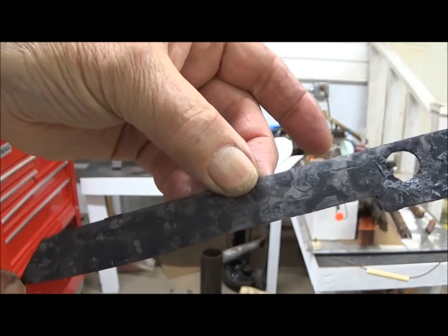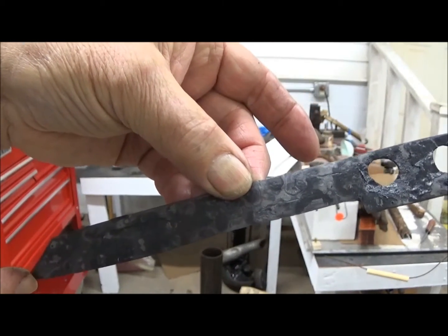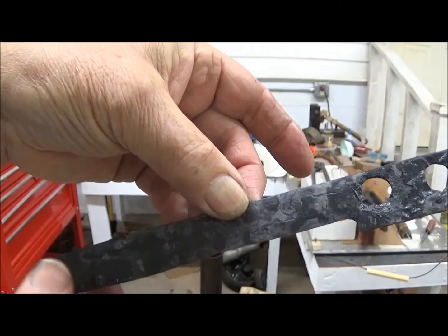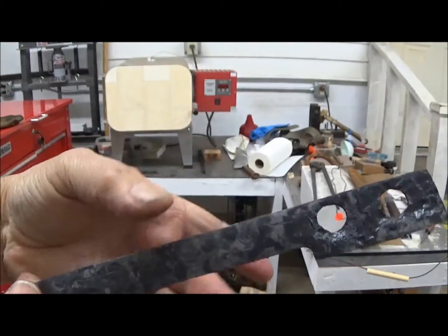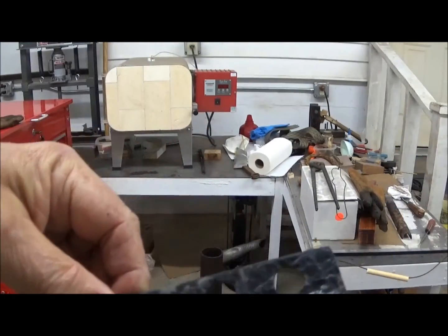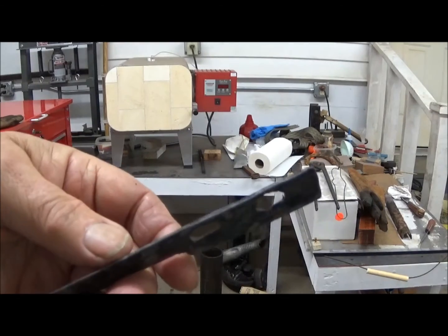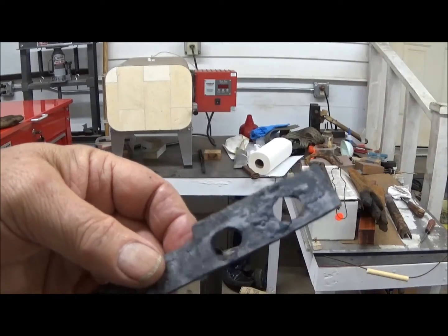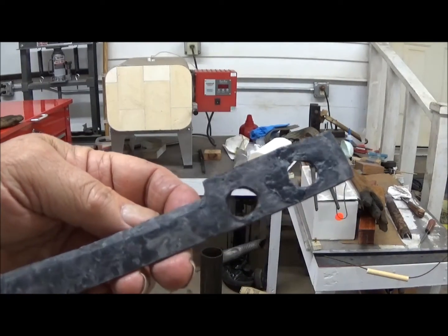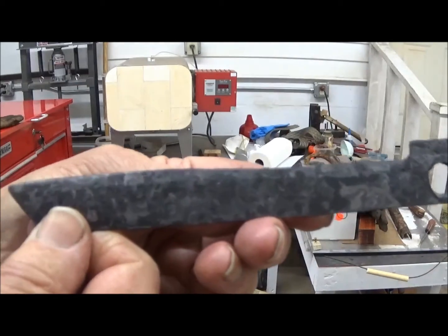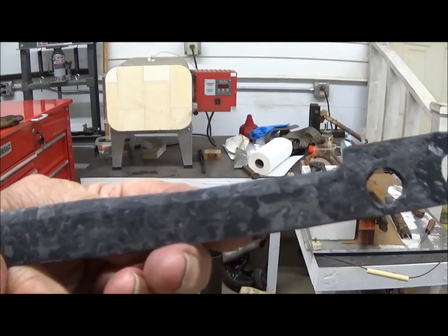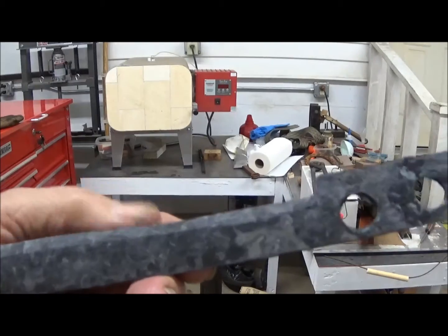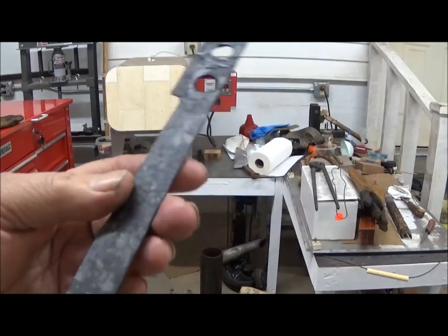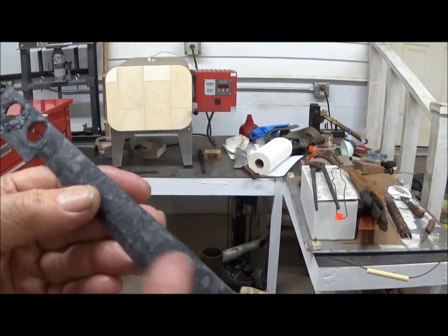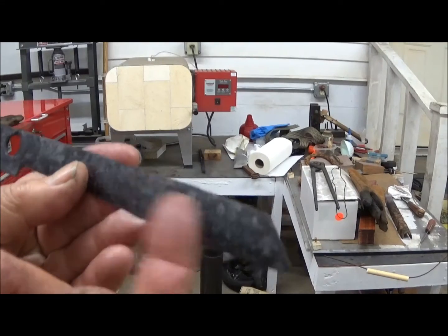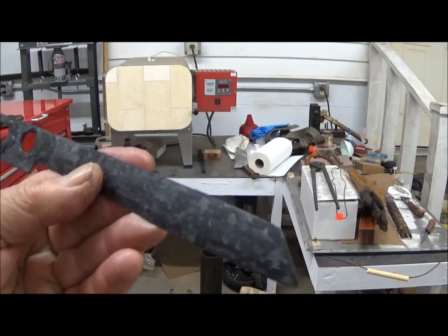The steel is actually shrunk a little bit, both in thickness this way and in thickness this way due to the heat treatment. The amount of scale, the amount of oxidation could have been decreased had I put a wrap on it, and perhaps on second thought I should have, but I didn't. So we got what we got, and we're going to put it back on the belt sander and see how deep those cracks go and see if we can salvage this blade.